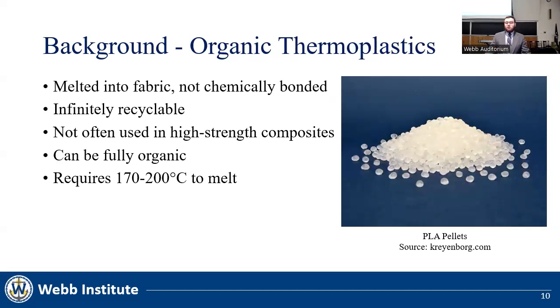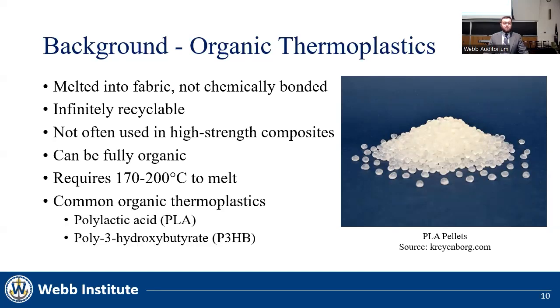The other matrix that can be used are thermoplastics. These are melted into the fabric instead of chemically bonded. This makes them infinitely recyclable. They are not often used in high-strength composites due to their slightly lower strength. However, they can be fully organically based, and they require 200 degrees Celsius to melt, which could possibly damage the fibers. Some common organic thermoplastics are polylactic acid and poly-3-hydroxybutyrate, which have similar properties to plastics used in the petrochemical industry.